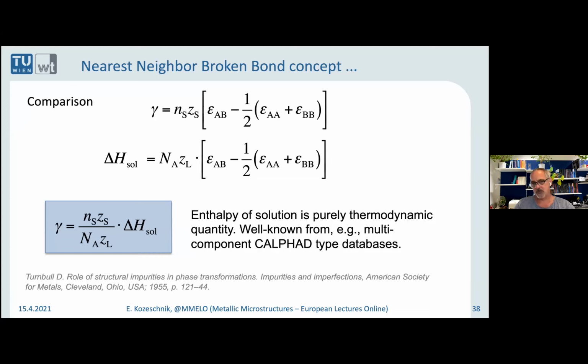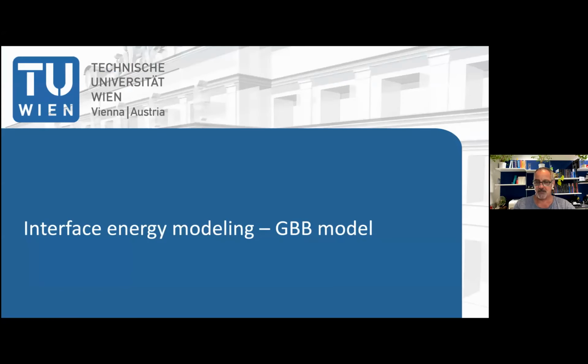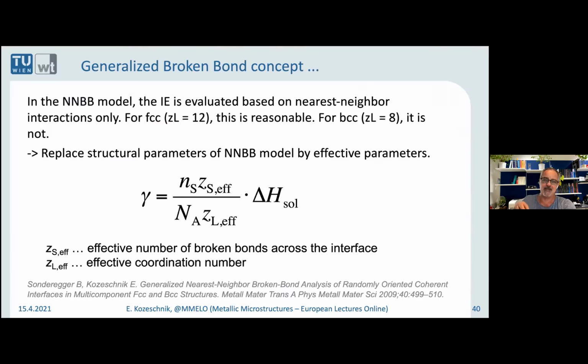So what we did was we thought about, okay, what could be the problem in this equation? Why is it giving incorrect predictions, particularly in BCC systems? And that was a cooperation that I had with Bernhard Sonderegger for many years, where we developed the generalized broken bond model with the simple idea of saying, okay, maybe the next nearest neighbors are not sufficient interactions to count.